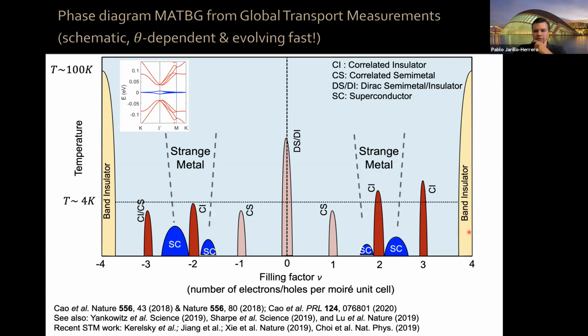And then, as I mentioned, at each integer, something happened. We had some signatures in transport of something happening. For example, correlated insulator at 2 and -2, very often also at 3, we see it. And then at 1 and -1, often a correlated semi-metal behavior. It's not an insulating behavior, but it's a resistance peak that occurs there. Here, this is rarely seen. This is quite frequently seen. And then at charge neutrality, you have a Dirac semi-metal, occasionally a Dirac insulator type state. In this region, you have strange metal behavior, and then you also have some nematicity and all these other things that I just mentioned. This was all information that we had obtained from transport measurements.